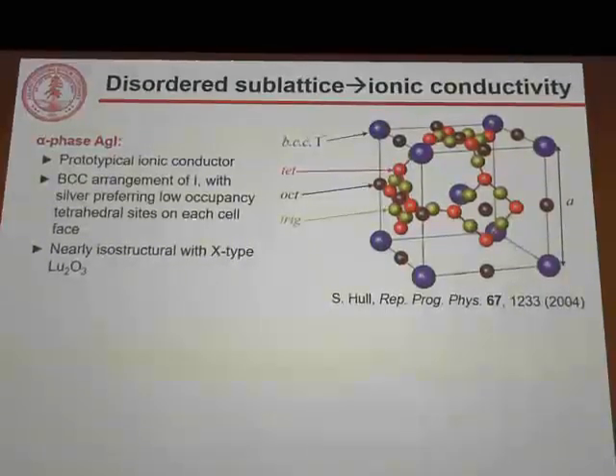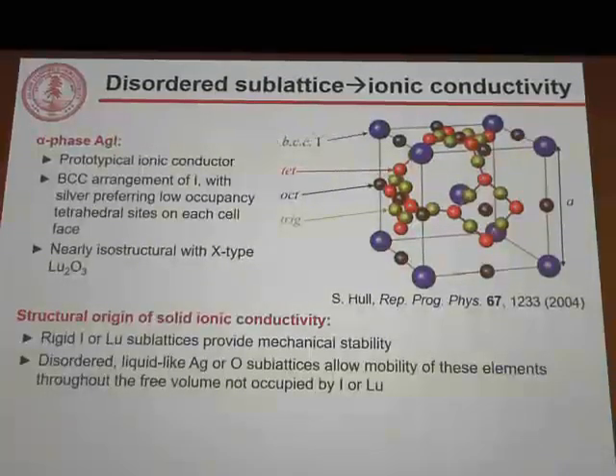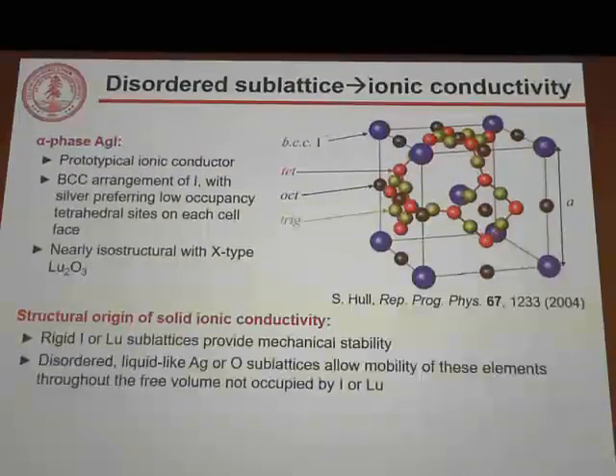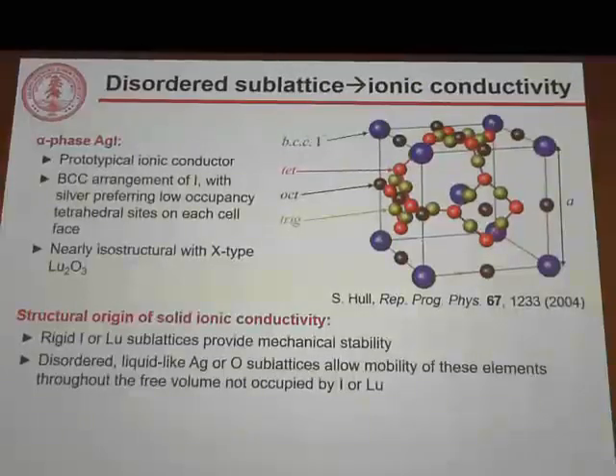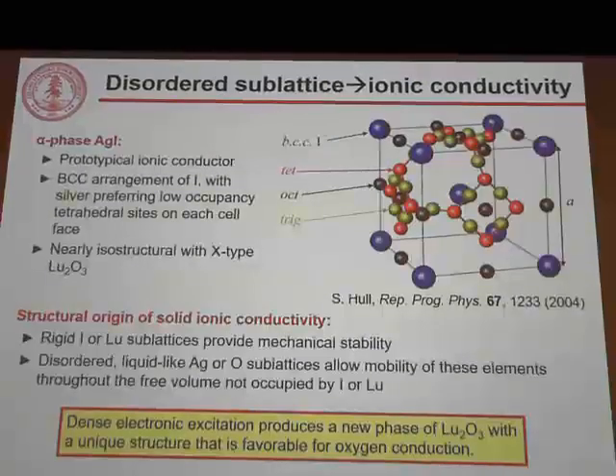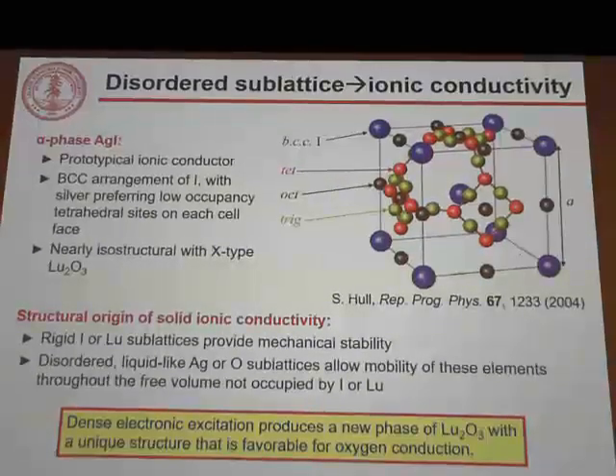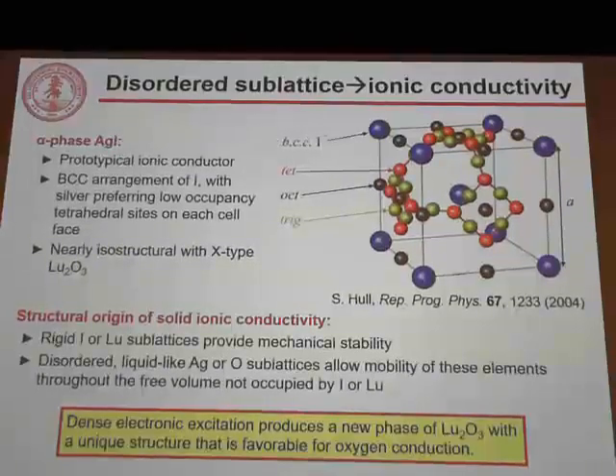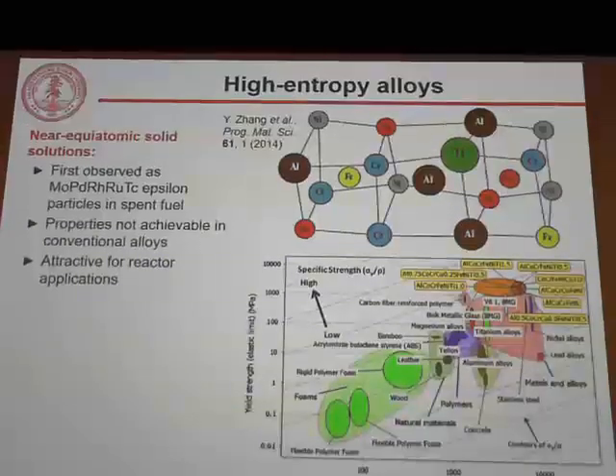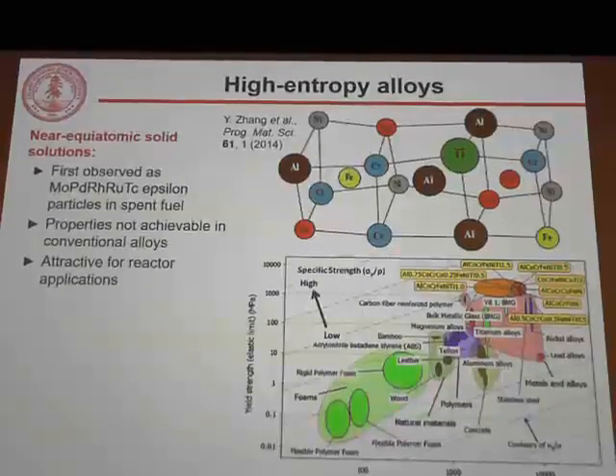And in fact, the exceptional ionic conductivity of silver iodide emerges from its unique structure. It has a rigid sublattice to provide mechanical stability coupled to a liquid-like sublattice where ions can travel freely through the free volume not occupied by the rigid sublattice. So its ionic conductivity emerges from this unique disordered structure, which is nearly the same as that of lutetium sesquioxide. So in this case, dense electronic excitation has, for the first time, produced a new phase of lutetium sesquioxide stable at ambient conditions such that it can be used in applications, which has a unique structure that is highly favorable for oxygen ion conduction.